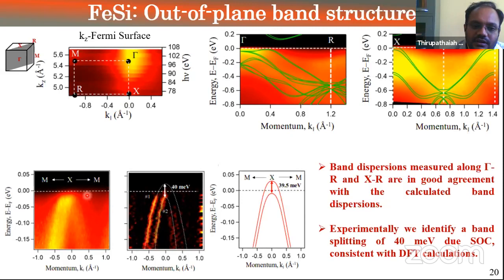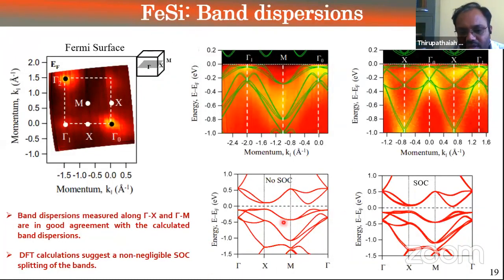And interestingly, we also measured along the MXM direction, where we have two bands. It's because there are no other bands contributing here, unlike here. It's a very complicated band structure, but along this direction, it's a very simple band structure. As you can see here, there is a band splitting. Initially, we did not understand why there are two bands, although our without-SOC band structure shows only one band, as you see here. Along the XM direction, there is only one band dispersing from XM.